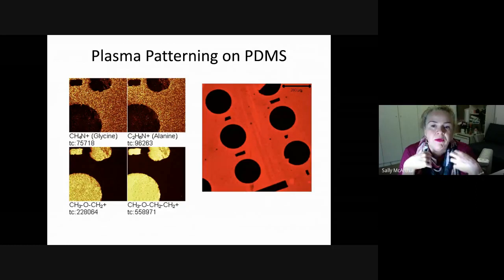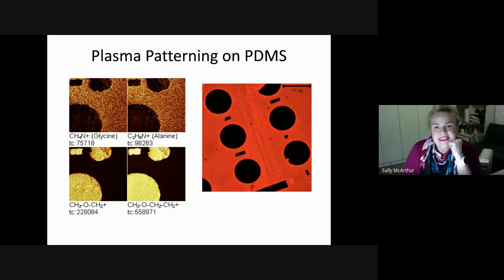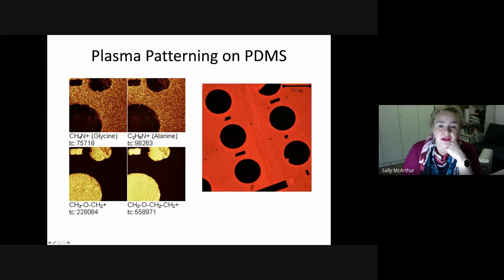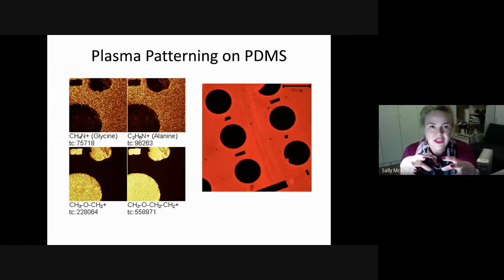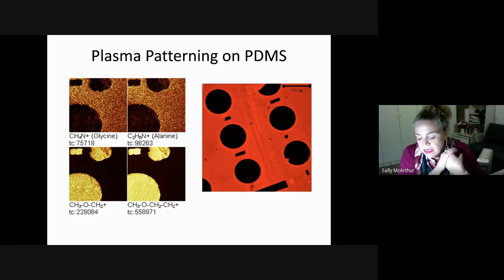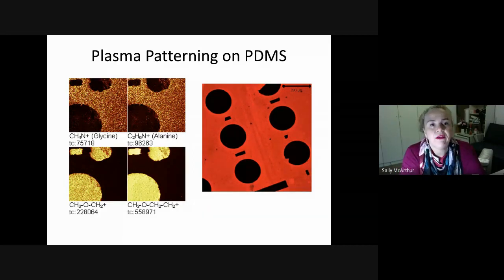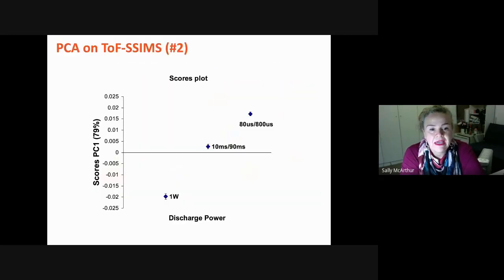Now, we can obviously then translate that over into a fluorescence image where we fluorescently label the protein, or we put a fluorescent antibody to the protein onto the surface, and that then detects. And so we've got bright areas here where the protein is stuck, and dark areas where no protein is attached. This is the tetraglyme area, and this is our anhydride area. And we can actually deposit this into channels and into silicone microfluidic platforms, or build up devices that way as well. So this is getting to that point of why plasma polymerization.